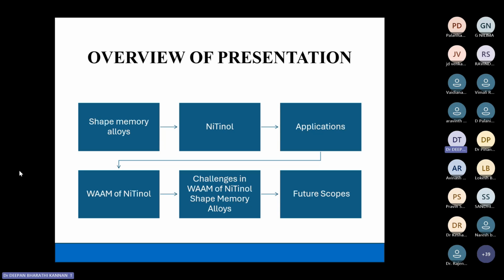Basically, nitinol exists in two phases. One is the high temperature stable phase, that is austenite. The other is the low temperature stable phase, martensite. The crystal structure of austenite and martensite is shown in the slide. Austenite exists in a simple cubic structure and martensite in monoclinic. In addition to these two stable phases, depending upon the processing that we do on the nitinol, there may be a possibility for the formation of R phase, whose crystal structure is trigonal. If it forms, it will have a negative effect on the properties of the nitinol.